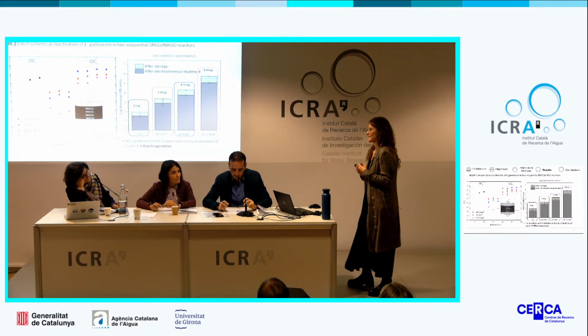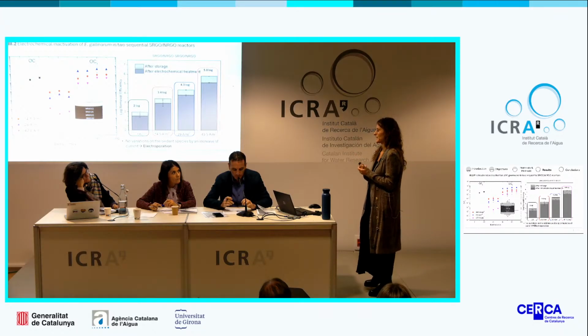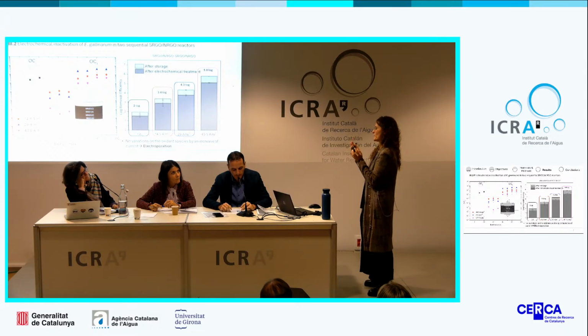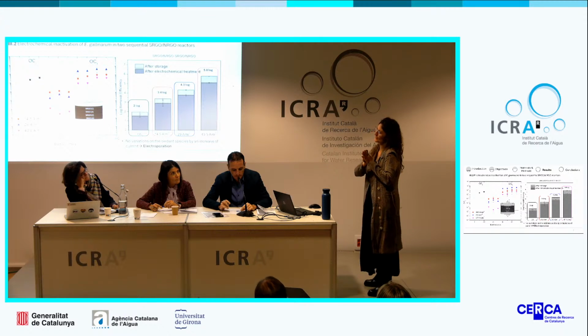Yeah, this is a bit complicated to distinguish, because to measure the direct oxidation, we will probably need linear sweep voltammetry. And in that case, it's really difficult to distinguish, because the oxidation of our antibiotics usually occurs in the same peak as the oxygen evolution reaction. So for that reason, we cannot really quantify which part is direct oxidation and which part is not.